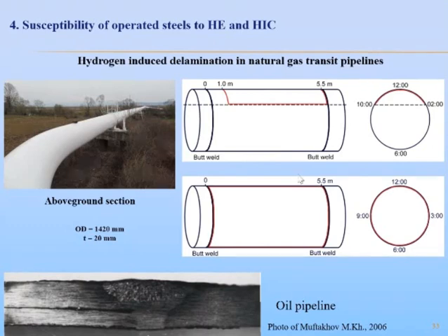Of course, the problem of extensive delamination is associated with preliminary metal degradation during long-term service. So more operationally degraded pipe steel due to microdelaminations is more sensitive to hydrogen-assisted macrodelamination. And the phenomenon of macrodelamination is clear for above-ground pipelines transporting natural gas, and it can be assumed that the main reason for its formation is pipe steel hydrogenation as a result of internal electrochemical corrosion.